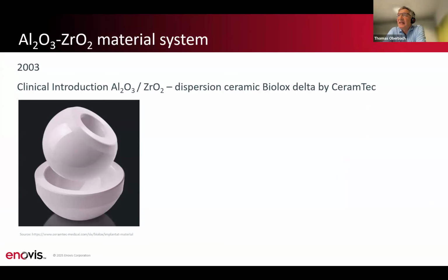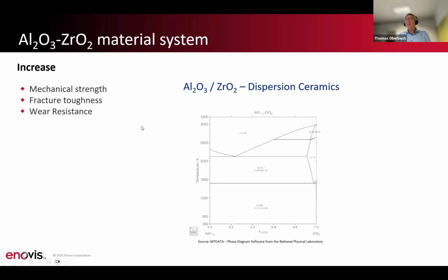And then in 2003 we have seen the clinical introduction of so-called dispersion ceramics or mixed ceramics by Ceramtec. Ceramtec is the market leader in this field, and most of the ceramic implants which are implanted worldwide come from Ceramtec. And they introduced in 2003 their Biolox Delta material, which is a ZTA ceramic. That means alumina based and toughened with zirconia. Also in our company, we have thought about new ceramic materials with a higher mechanical strength in comparison to alumina, with a higher fracture toughness and a higher wear resistance.